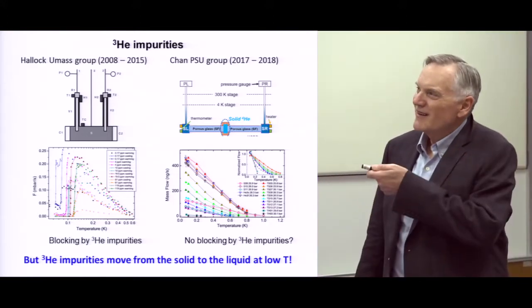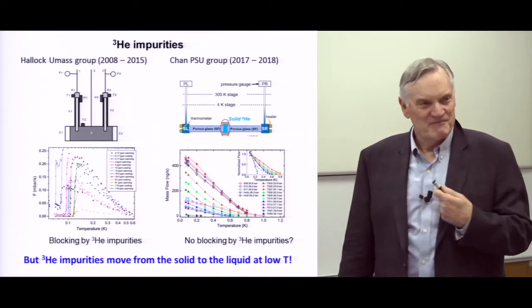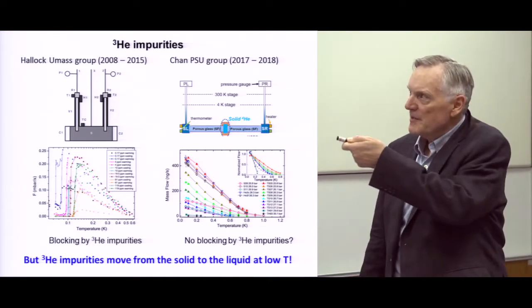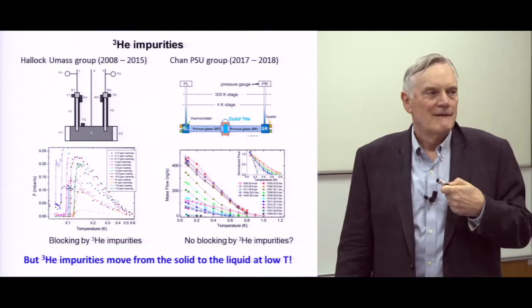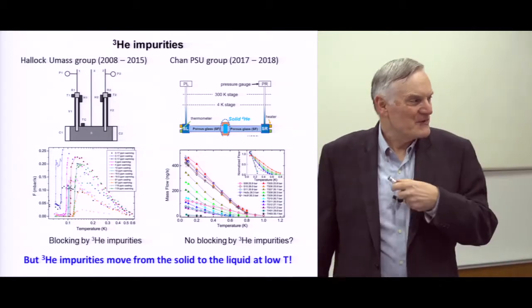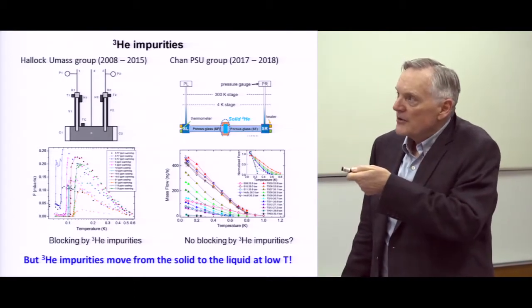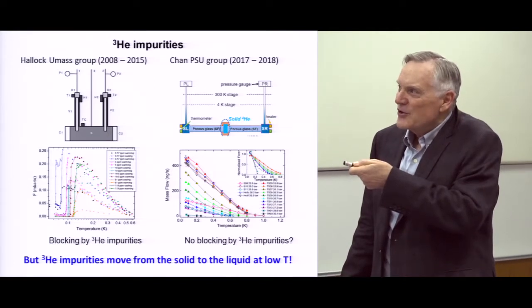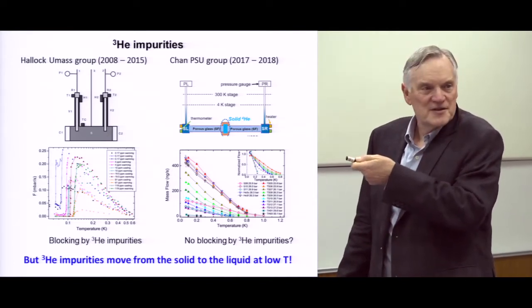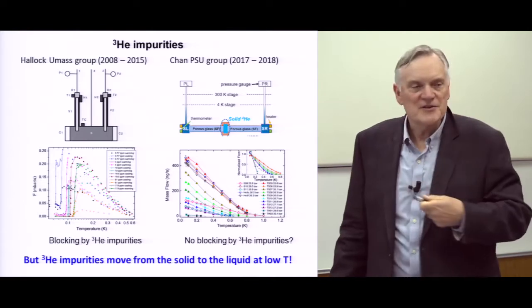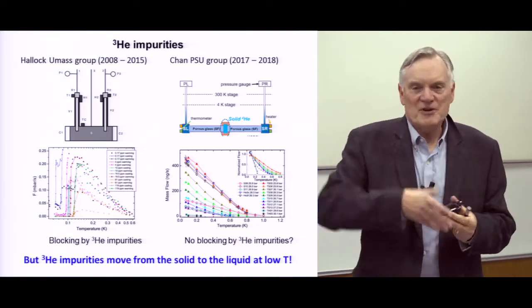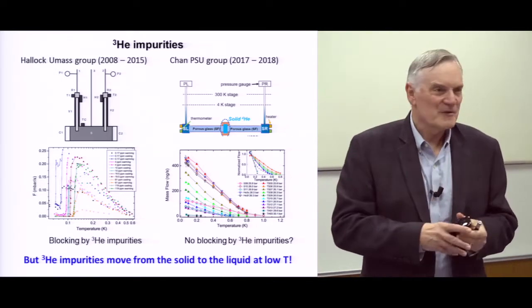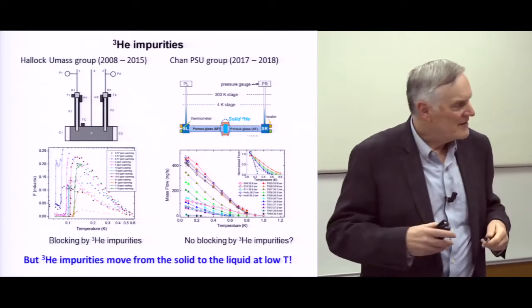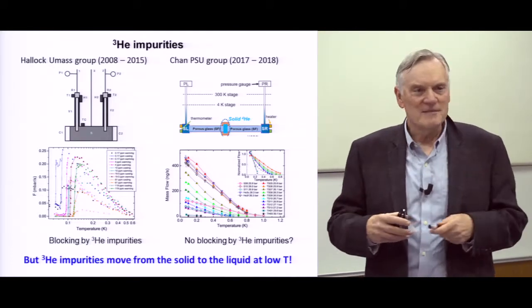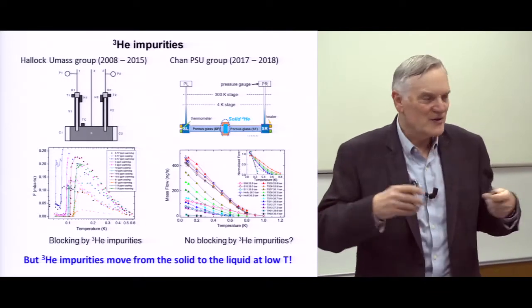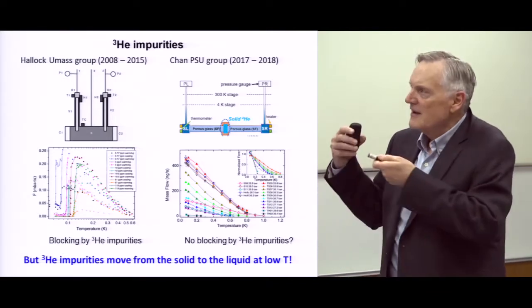Yeah. The current effort that's trying to really pin that down is this experiment at Penn State. There's a paper that has been under review for some time, I believe. But in this geometry, they tried to do everything they could to show that it's not at the boundaries, that it's through this piece of solid. So in the middle of it, they put a block. They just put a piece of metal in the middle of it to see if it stopped the flow. And then they put, I can't remember what all they did. They put aerogel to pin things down, to prevent dislocations from moving.